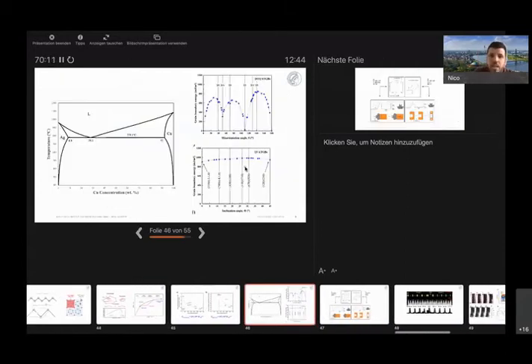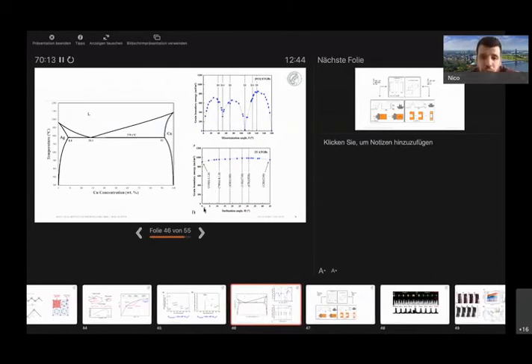Yes. So if you look now, this is the inclination angle, no longer the orientation angle, going from 0 to 45. And this is basically going from the 310 boundary to the 210 boundary. So you can see that the 310 boundary has a little bit lower energy than the 210 boundary. And this is all the asymmetric rotations that you can have in between.